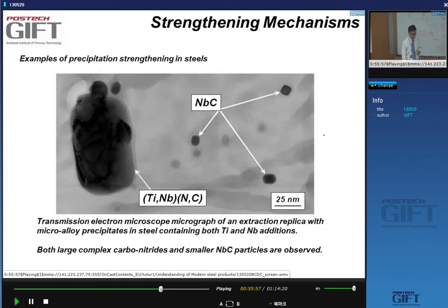Okay. But in general, what we have are these nitrides or carbides of microalloying elements such as niobium, titanium, and vanadium. It's very important to control the size of these precipitates. For instance, in this picture here, these particles are too large to give any strengthening. Yes, you need particles that are of the order of 5 to 10 nanometers.